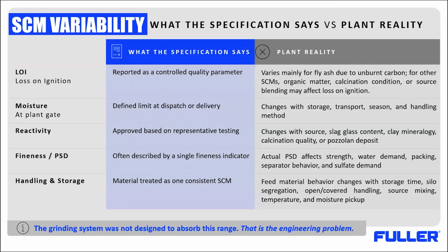So the next issue is what actually reached the mill. On the material certificate, the material may meet the specification. Loss of ignition, moisture, reactivity, fineness, all within limits. But in operation, in reality, the mill doesn't grind the certificate. It grinds material arriving at the feeder. So between dispatches and dosing, the material can change.